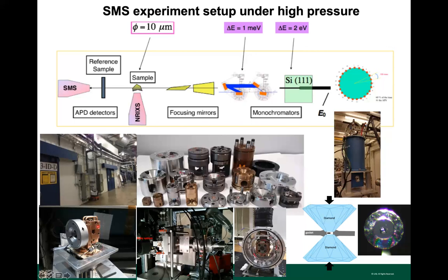Several years ago, we developed this small diamond cell that can go onto this cryostat with this special tubing going around the sample holder. We can cool this diamond cell to around 10 Kelvin. And this is a design by Stas: this big regular-size membrane is used to change the pressure in situ at any temperature.